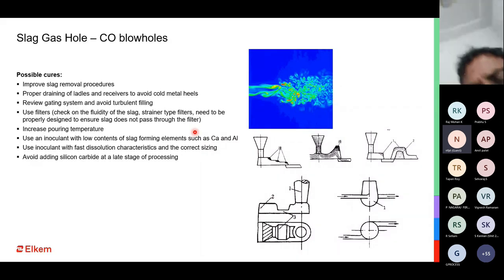So we have to make sure that any vessel which is handling the liquid metal, be it the treatment ladle, be it the pouring ladle, be it even the tundish cover of the treatment ladle, has to be very clean, and there should not be any deposition of slag in it, which can eventually cause you inclusions or defects. We have to make sure that the flow of metal is as smooth as possible and you do not have a lot of turbulence inside the gating system.